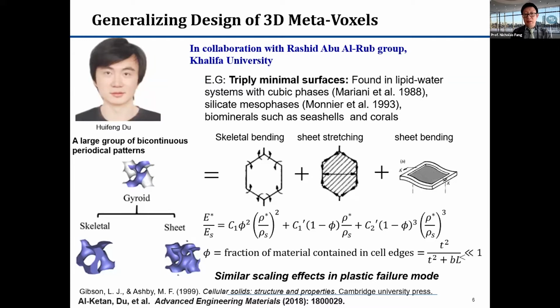And it turns out that if we are trying to examine the mechanical behavior of such elements, you can group them into the different deformation modes that are basically distributing the load by the skeletal bending, stretching, as well as sheet bending modes. And each of them has different scaling laws in terms of reducing, for example, the weight or volume ratio of individual elements. And interestingly, this scaling effect can also be deduced, not only in the elastic domain, but also in the case where the structure is under large deformation, for example, densification as well as plastic failure.